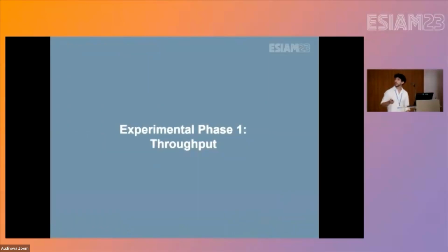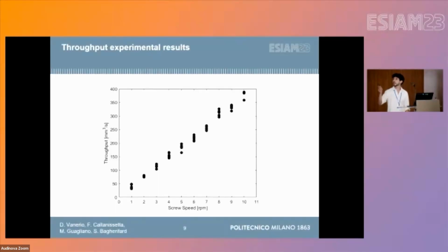So first results for the experimental phase are the ones regarding the throughput. We obtained a pretty good law, pretty simple. We decided to do a linear regression with zero intercept, because naturally when we have null screw speed, we also have zero throughput. We found a p-value of 0 and an R-squared value of 99.19. So we consider this law basically validated.